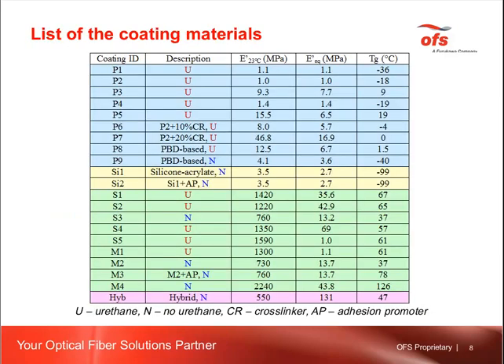So for this study, we selected a long list of coatings. Most of them are commercially available, so we got them from different manufacturers. There is a list of primary coatings from P1 to P9. We also used two silicone coatings, Si1 and Si2. These silicone coatings are UV curable. They have acrylate groups in them. There is a series of secondary coatings from S1 to S5 and a list of monocoats from M1 to M4.